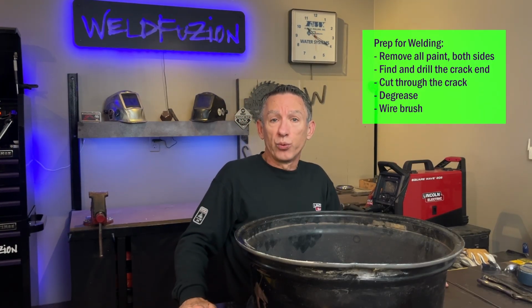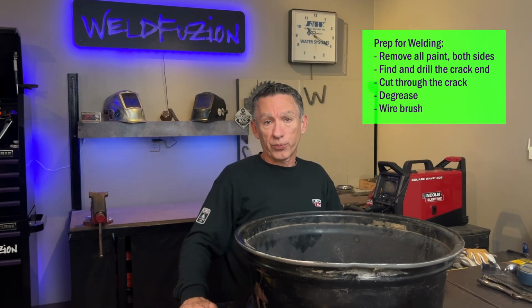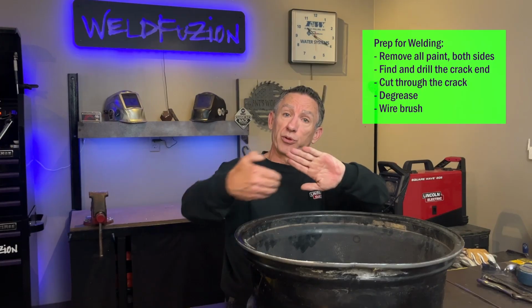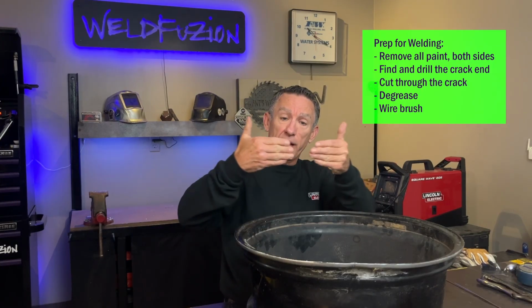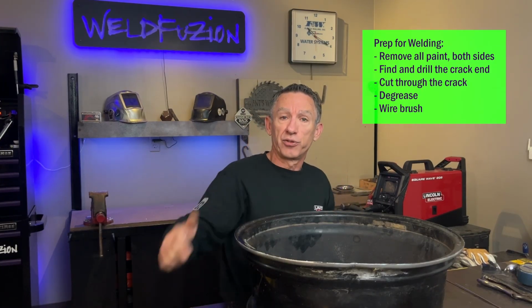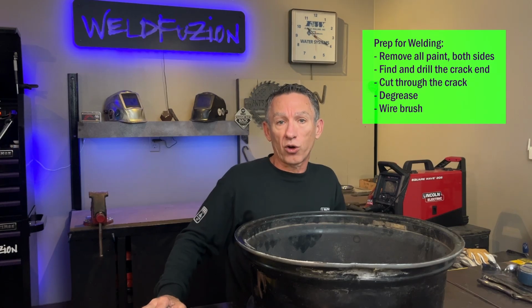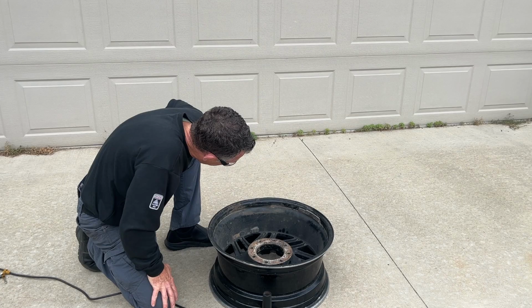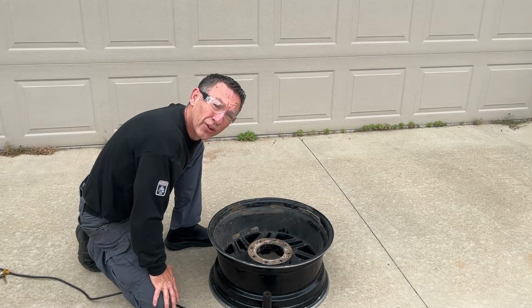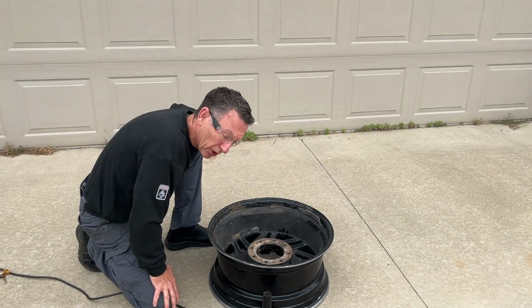And what we're trying to achieve here is good penetration all the way through, right, with the potential to come through on the back side so that we've got good overlapping penetration in the center of the weld and nowhere for that crack to restart again. That's our goal. Let's see if we can pull it off. So I've got this thing outside so I can see exactly what I'm looking at for that crack.